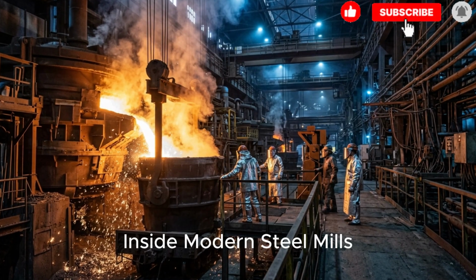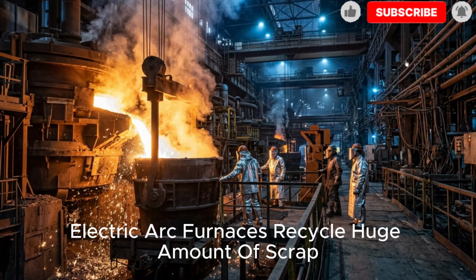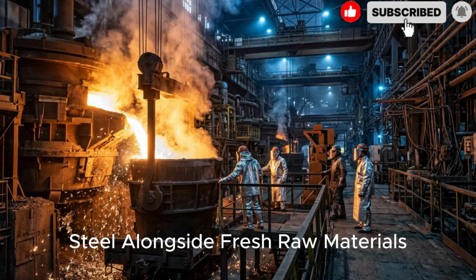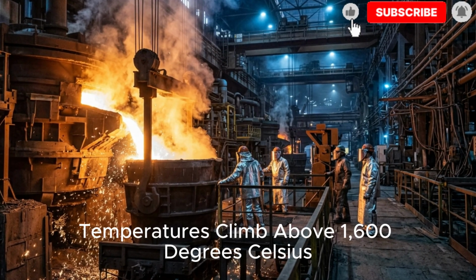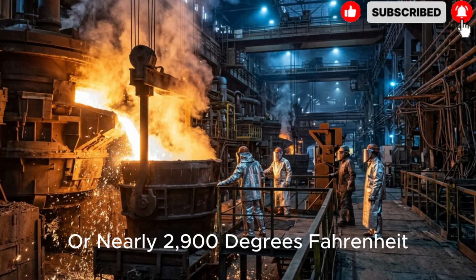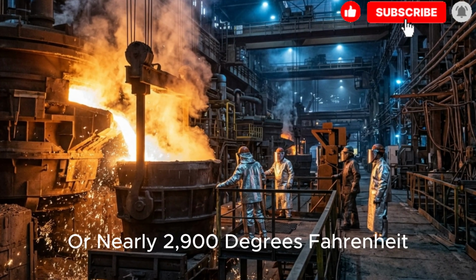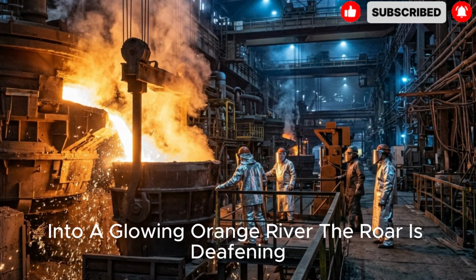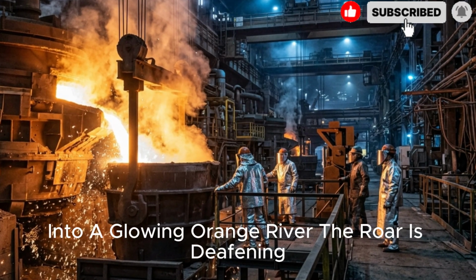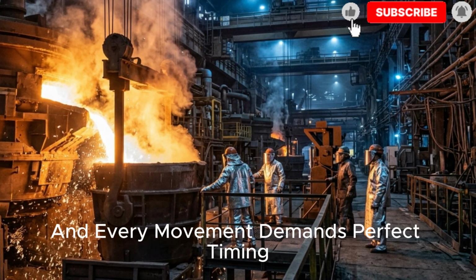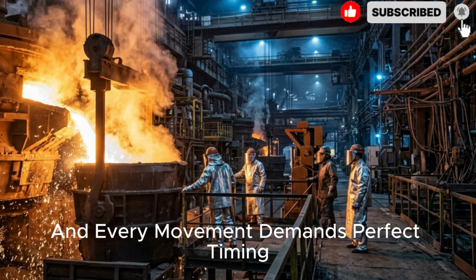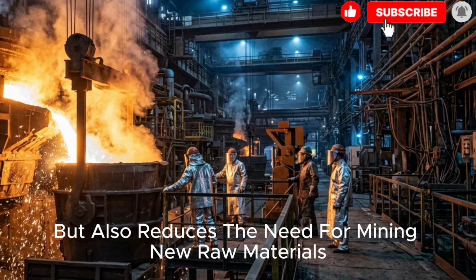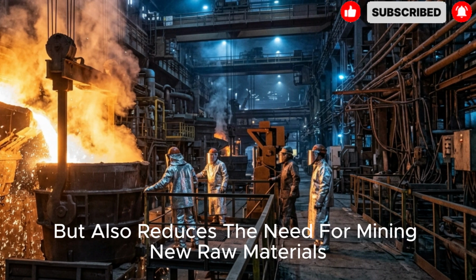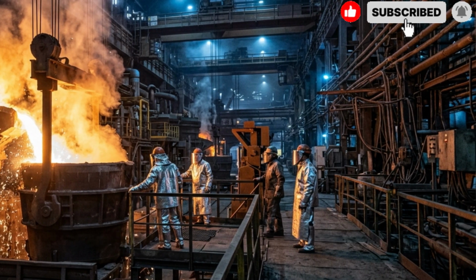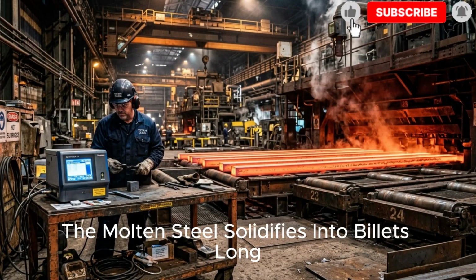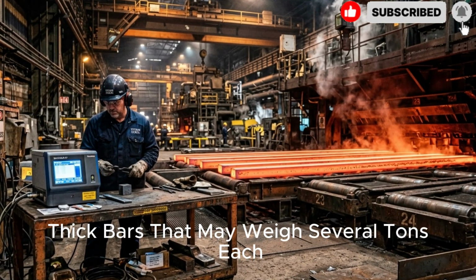Inside modern steel mills, electric arc furnaces recycle huge amounts of scrap steel alongside fresh raw materials. Temperatures climb above 1,600 degrees Celsius, or nearly 2,900 degrees Fahrenheit, hot enough to melt solid steel into a glowing orange river. The roar is deafening, the heat feels overwhelming, and every movement demands perfect timing. This process not only creates premium steel, but also reduces the need for mining new raw materials, cutting energy use and emissions. The molten steel solidifies into billets, long, thick bars that may weigh several tons each.